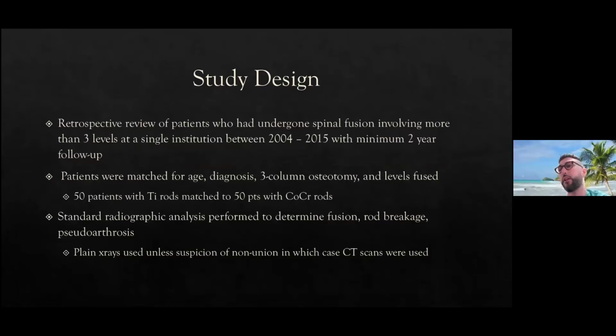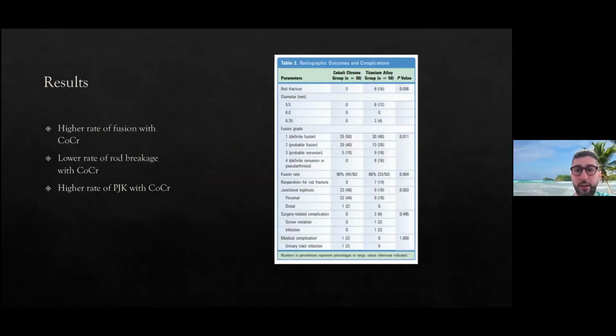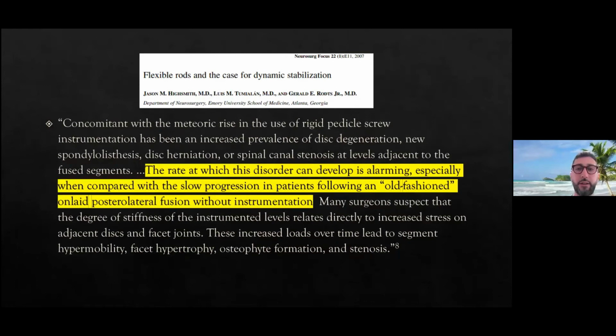And they used x-rays, and if there was evidence of a pseudoarthrosis, a rod breakage, then they went and looked at the CT scans. And here's basically the summary of the results. This is kind of all you need to know about this study. There was a higher rate of fusion with cobalt chrome. There was a lower rate of rod breakage, but there was a higher rate of PJK. So clearly that is a factor to consider.